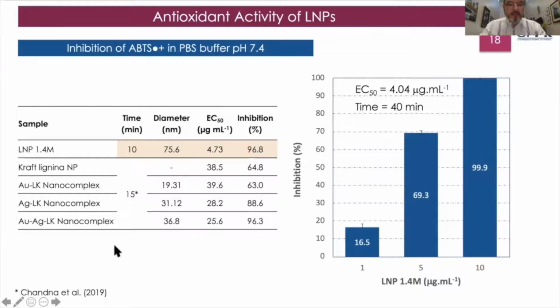The only material that actually approached the inhibition level obtained with our particles was this nanocomplex between lignin, Kraft lignin nanoparticles with gold and silver nanoparticles. And although the inhibition was as high as 96% for both, inhibition was the same, but then the EC50 for our lignin nanoparticles was much lower.